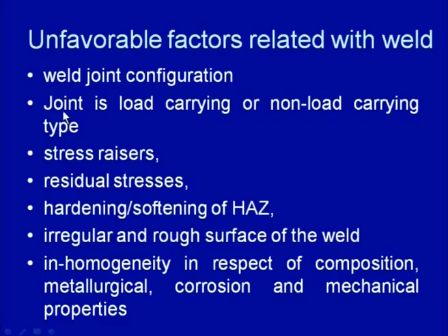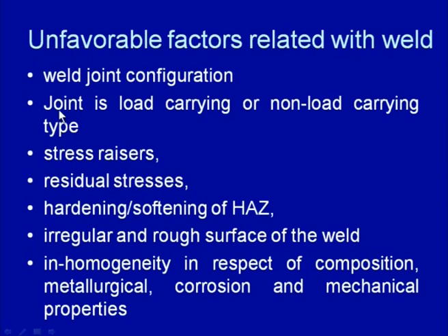And these unfavorable features, which adversely affect the performance of the weld joint under fatigue conditions, include the weld joint configuration. For example, fillet welds offer very poor fatigue life as compared to groove butt welds. Also the type of joint, whether the joint is load carrying or non load carrying.